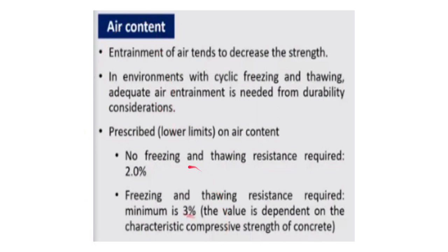Okay, so in case of HSC, if the air entrainment is too high, it will very drastically reduce the strength and its intended purpose will not be served. But it should have a minimum of 2% if there is no freezing-thawing resistance requirement, and 3% for freezing-thawing resistance requirement. Okay, so that is sufficient.